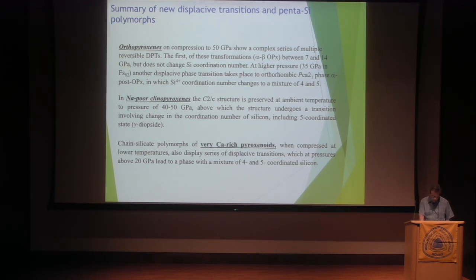And then in chain silicate polymorphs of very calcium-rich pyroxenoids, when compressed at lower temperatures, they also display a series of displacive transitions, which at pressures above 20 gigapascals lead to phases with a mixture of 4 and 5 coordinated silicon. However, none of the observed high-pressure phases with pentacoordinated silicon are quenchable, so they don't really add to the library of phases with pentacoordinated silicon that we could find on the surface. They would only be present at depth.